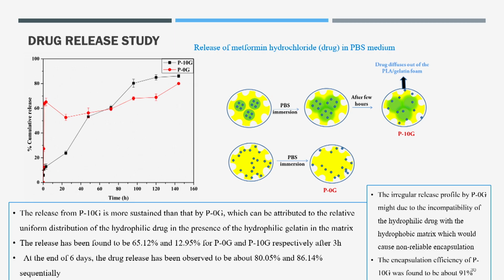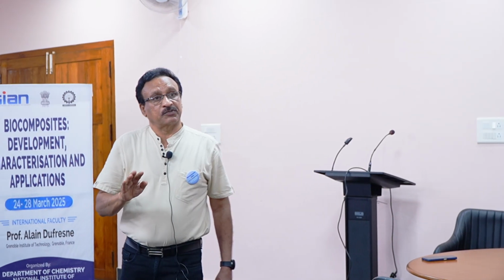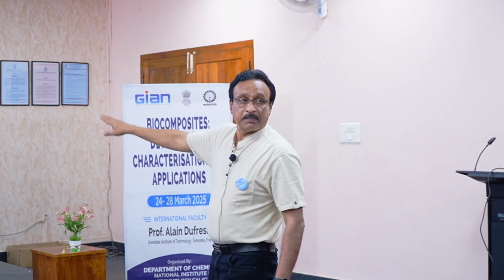But if you look at the black graph, it is not a sudden release. Slowly over a period of time it diffuses, and the final release from the black graph is above the red graph. Means over a period of time, higher release will happen from the gelatin loaded system, right? And that release is more consistent. If the drug is suddenly released into the body, activity will be less, but if it is released slowly, activity will be higher and uniform. So it means that gelatin has effective control. Gelatin is a good matrix for controlling the release profile. So I have given a mechanism on the right hand side.